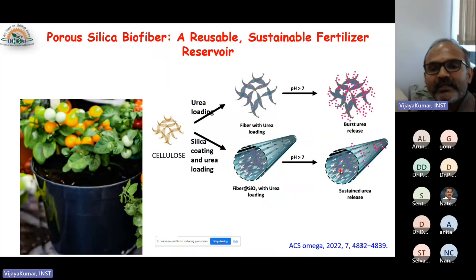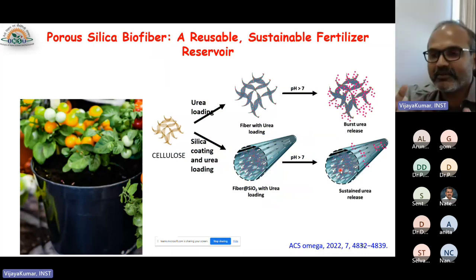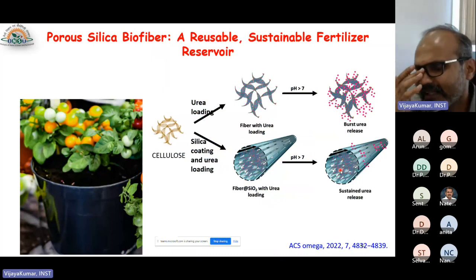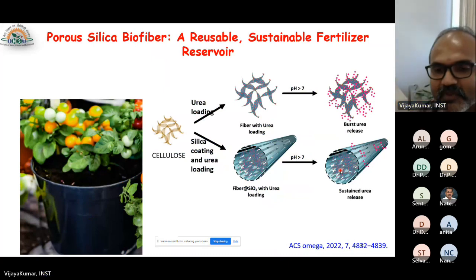One other important application of giving a silica coating on the cellulose is it will give a shape memory property for the cellulose. Say for example you are taking cotton and sinking it into the water, it will become a thin film. Whereas if you are coating it with the silica, it will have a shape memory property. After adding water, still it will be able to keep the same volume that it is occupying. Not same, relatively same. So having that in mind, we have used the same jute coated with silica as a reusable fertilizer matrix.